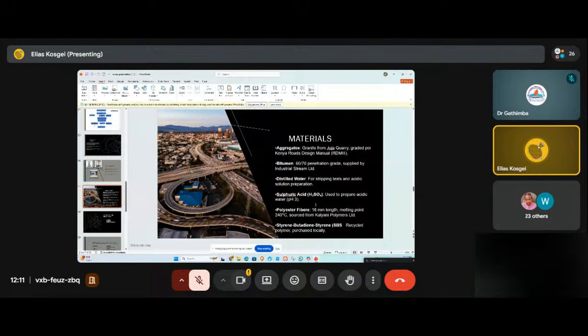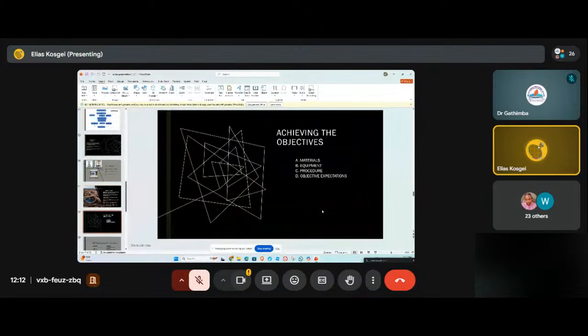And sulfuric acid, we also need sulfuric acid to prepare the acidic water of less than pH 3. We'll be needing the polyester fibers, specifically 18 millimeters in length, and it will be melted at 240 degrees Celsius. We'll be sourcing this from Kalyani polymers right here, and then the final material will be the Styrene-Butadiene-Styrene recycled polymer purchased locally.